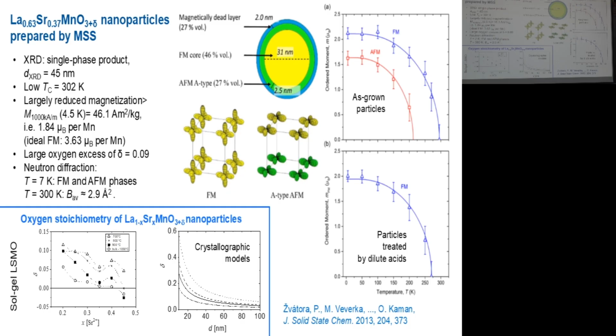And for example, at the end we found that they have a complex structure with a ferromagnetic core, an antiferromagnetic shell, and above that there is another magnetically disordered shell. And we even evidenced a certain gradient of strontium within the particles, that the concentration of strontium was increasing towards the surface layers because of some kinetics of the growth of particles in the flux. So maybe I'm going too much into details, but I'm just showing that you cannot disregard the synthesis. You cannot disregard the procedure. It is not only about the nominal composition, about the size of particles, but the different synthesis can really affect the material extremely, and can shape the final properties and completely alter the properties.